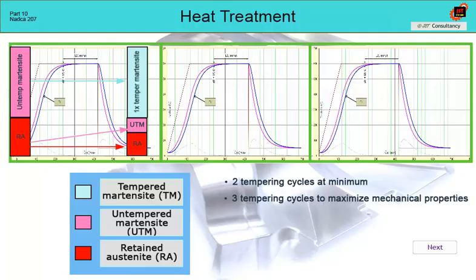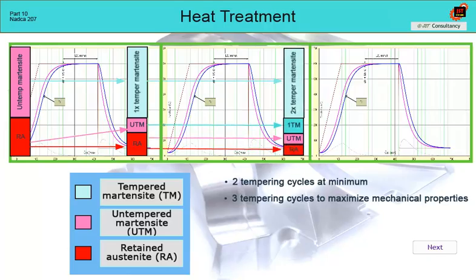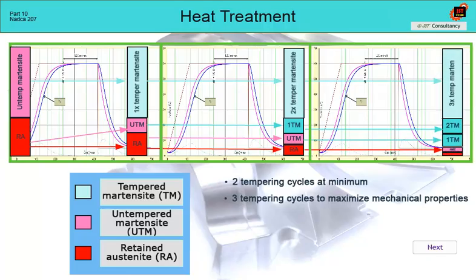Only in the second tempering is the first part of the martensite tempered twice, the second only once. This may be sufficient for some applications, but where there is a requirement for maximum mechanical properties and dimensional stability, a third tempering must also be included, which ensures that the majority of the martensite will be tempered at least twice.